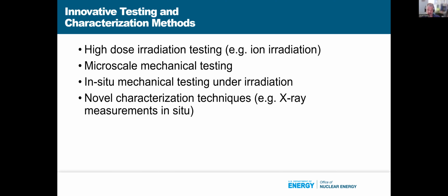And then it does take a long time to do these irradiations. And also sometimes it's very important to be able to measure that property under irradiation. So in situ, maybe creep. We did point out in some of the industry needs that fatigue was a need for some of the molten salt chloride reactors. Fatigue is a very difficult measurement to make even after irradiation, but it's really not that applicable after. It's really something that has to be done in situ. So in situ creep and in situ fatigue measurements under irradiation is really a critical measurement that I don't even know anybody that's doing it.